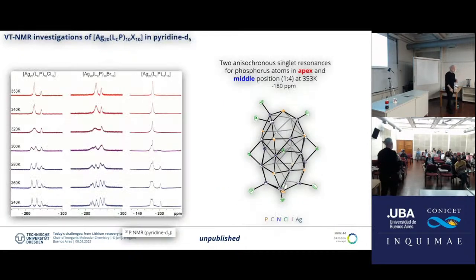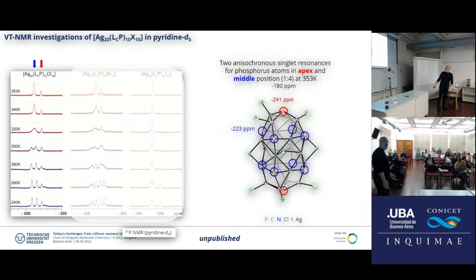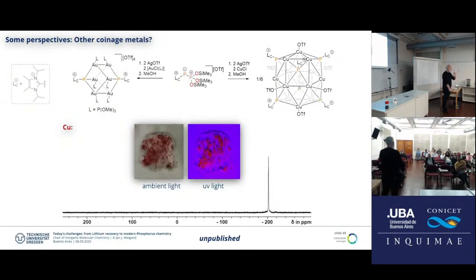And we can, last part before I come to the last part of my talk, you can see particularly the iodine ones at higher temperature, the NMR signal becomes a singlet, meaning that these clusters are wobbly in solution. So there is much, much more to gain by adjusting the reaction conditions, and we have already identified that we can even make a silver 26 cluster. And for this cluster chemistry, people would of course ask, what about copper and gold? And of course we've done the copper as well. Copper is more difficult than gold, silver, unfortunately. The yields are not that good, but we can do it, but they are fluorescent.